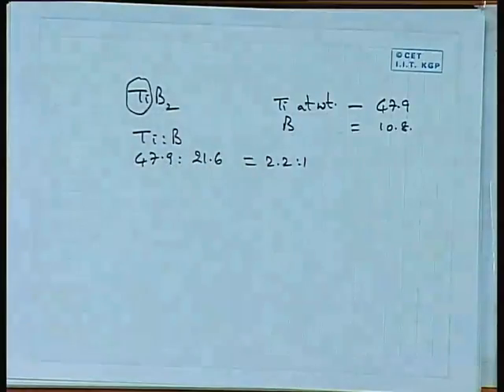If the ratio is not maintained, for example, if you have excess of titanium, what will happen? If you have excess of titanium, Al3Ti will form. The excess titanium, whatever is left out, will react with aluminum and form the Al3Ti. And if you have excess of boron, that excess of boron will form AlB2. So our objective is not to have these two phases, but to have only TiB2, and hence the process parameter control is very crucial.